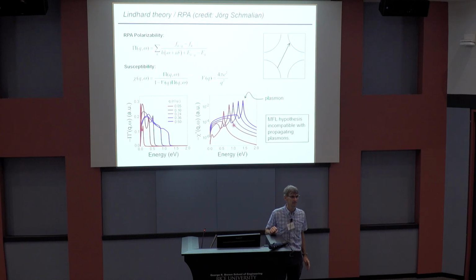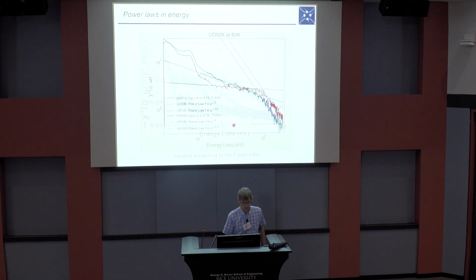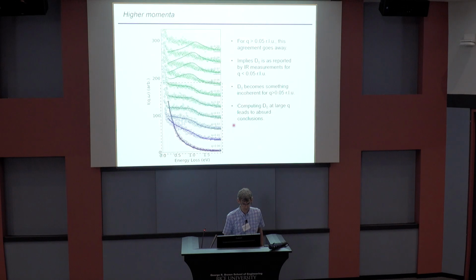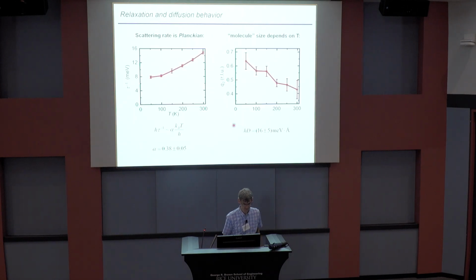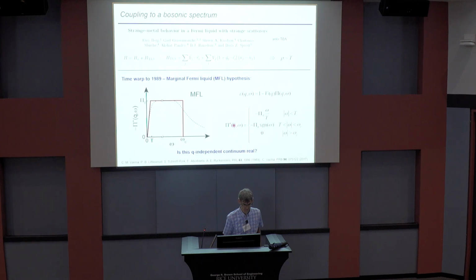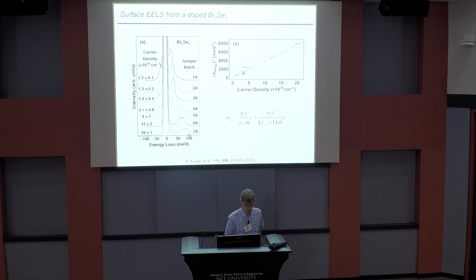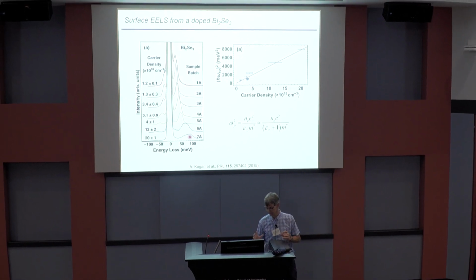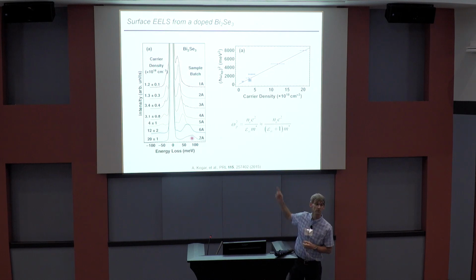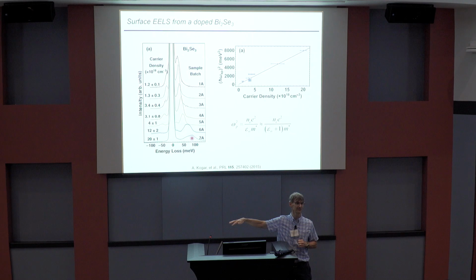Would you see it in bismuth selenide, since you gave the example of... Yes, we do. That's this peak. So bismuth selenide looks like, oh goodness, too many slides, I'm sorry. Here it is. This is doping dependence. If you look at the Q dependence of this, we didn't have great Q dependence at that time, it was 2015, but that's an ordinary collective mode. We change density and it shifts in a way that makes perfect sense, which also doesn't happen in the cuprates. The plasma frequency in the cuprates doesn't depend on where you are in the phase diagram. It couldn't care less how many electrons are in the system. That's already a hint that there's a problem.